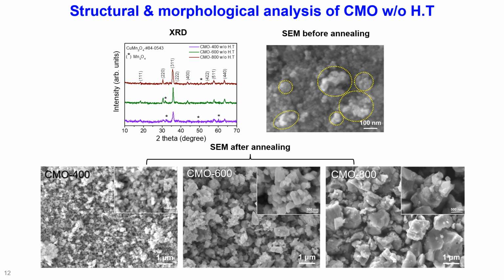In order to confirm that the faceted morphology enhances the electrocatalytic activity, we have synthesized the CMO nanoparticles via co-precipitation method, that is without hydrothermal method. So here the XRD shows the same CMO, that is cubic CMO phase of the nanoparticles obtained, but here there are some Mn3O4 impurity without HT treatment.